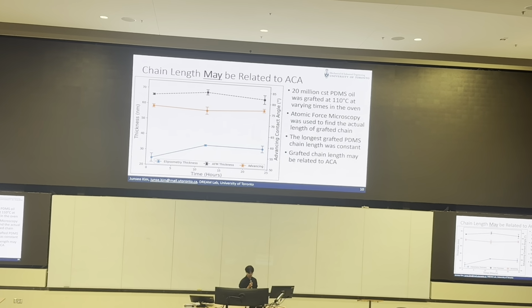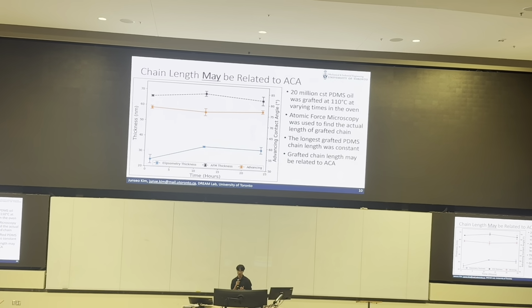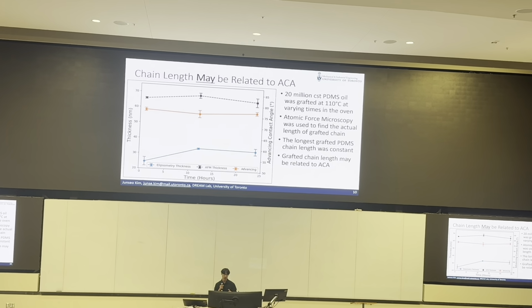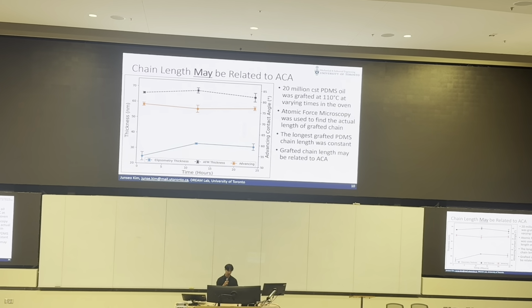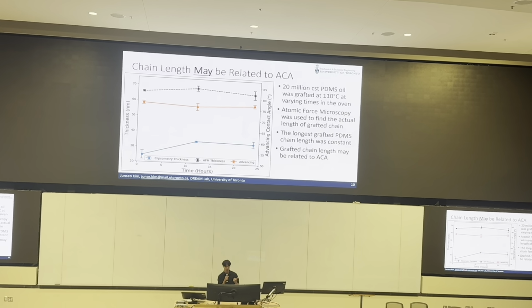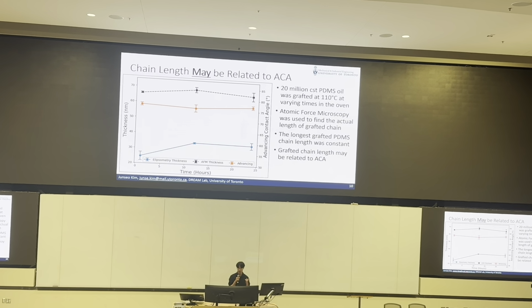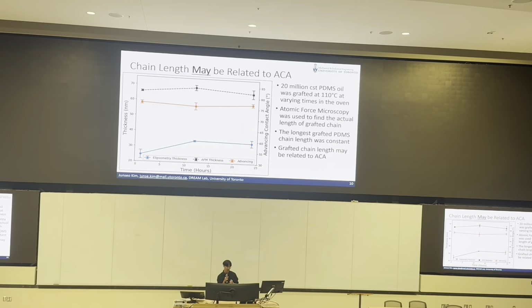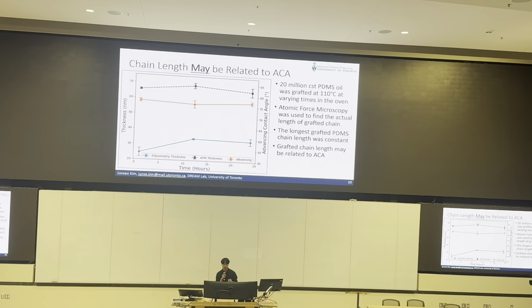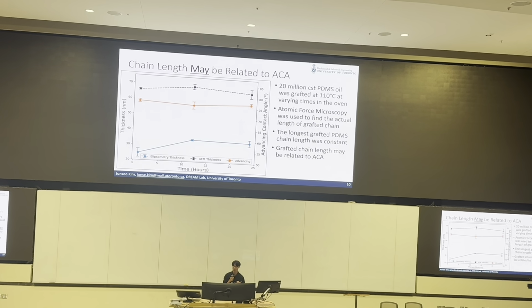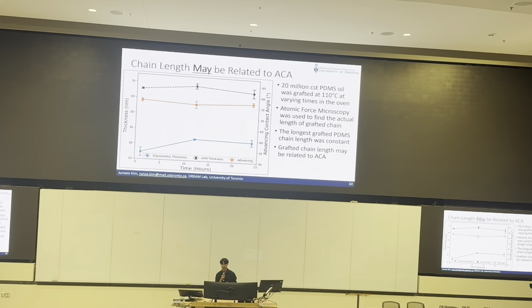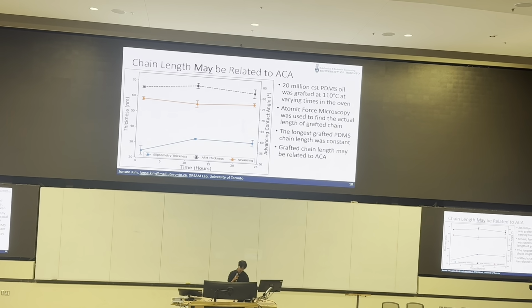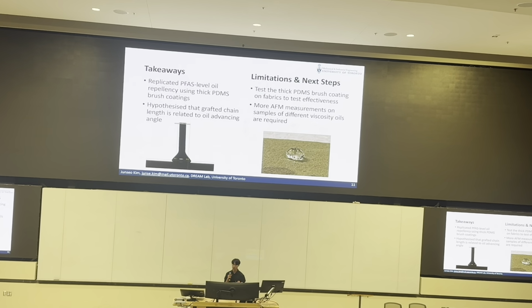So we did an AFM measurement, which is atomic force microscopy. That was used to find the actual chain length of the grafted chain. It's slightly different to the ellipsometer. What we found was that the grafted chain length is independent of the curing time or temperature. So that could potentially be what's related to the advancing contact angle or performance. Understanding some of the mechanics there, that was what we did.